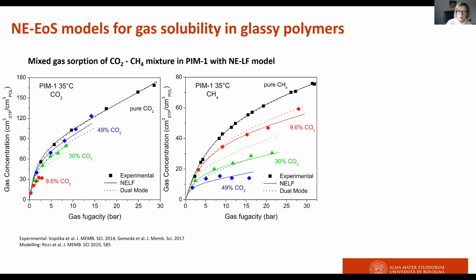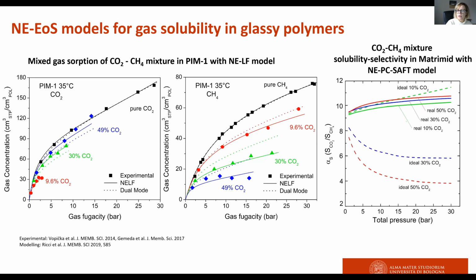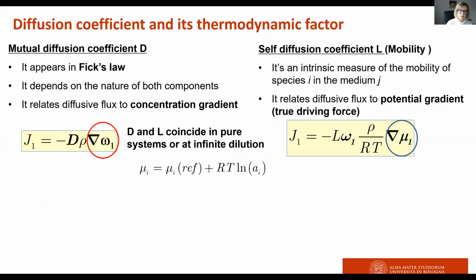And another example of a similar problem is reported here. We are considering here a different polymer, Matrimid, which is used in CO2 methane separations, and we are using a different equation of state framework, the PC-SAFT. Again, we are able to understand the competition effect, which only occurs during real multi-component simulations, which cannot be caught assuming an ideal behavior based on pure gas values of the solubility. This is something which is actually reported also experimentally.